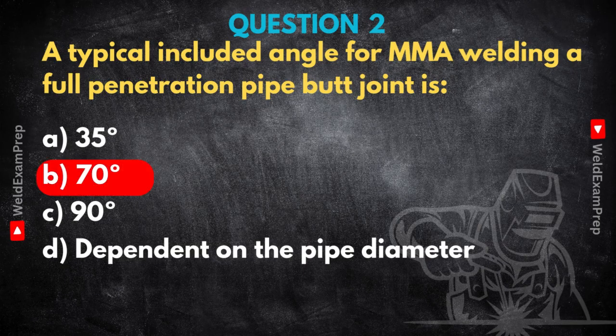Now, specifically for MMA welding, manual metal arc, what makes this 70-degree angle so important for a good full penetration pipe butt joint? Well, what's fascinating here is how practicality and the physics of the process dictate the design. For MMA, that 70-degree included angle for a full penetration pipe butt is pretty much the industry standard, widely accepted. Why? Because it gives enough access for the electrode. MMA electrodes can be quite chunky, right? You need room to maneuver. And that access is absolutely crucial for the welder to make sure they get proper fusion all the way through the joint, root to cap. Just imagine trying to weld down in a really narrow V-groove. The electrode would struggle to reach the root properly.